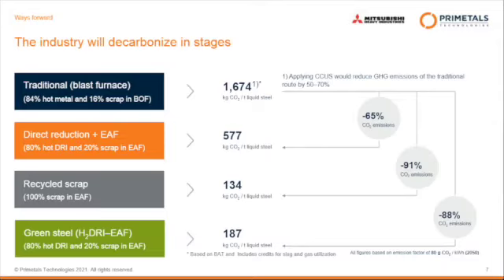On the one hand, direct reduction plus electric arc furnace. And as an example here, utilizing 80% DRI, 20% scrap in the EAF. So we can end up, even if we reduce with natural gas, it reduces the carbon emissions already by 2/3. So it's an essential way forward, even if we don't have the hydrogen or the green hydrogen yet at scale.